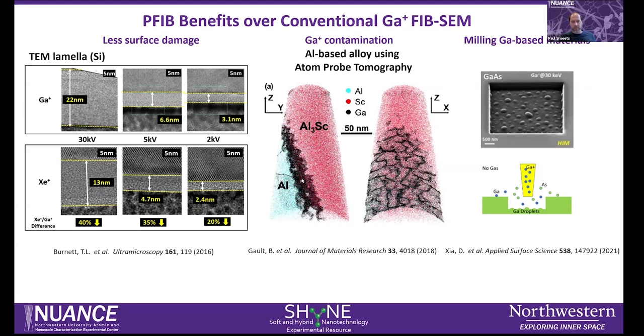When you prepare these samples with gallium, you will obviously get pollution of gallium near your grain boundaries. So if you want to investigate the native structure, that gallium beam would not be preferred for these type of materials.